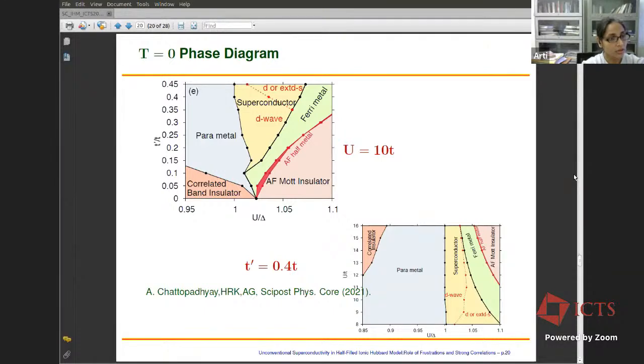And the most interesting feature, as I'm showing you, is that the superconductivity on one side starts on a charge density wave insulator, and on the other side it starts from an antiferromagnetic Mott insulator. But from either side you start, the transition into the superconducting phase takes place not directly from the insulator, but it always takes place via a metallic phase. So first the gap in the single particle excitation spectrum gets closed, by either increasing the electron-electron interaction as you are coming from the charge density wave band insulator side, or by decreasing the electron-electron interactions if you are coming from the antiferromagnetic Mott insulator side.